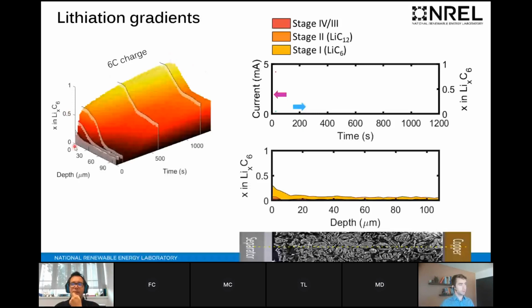So on this axis, we've got depth. 0 is close to the separator, 100 is close to the current collector, and then over time. And you can see at all times there's a severe lithiation gradient, but in particular at the beginning. Severe lithiation gradients where there's high lithiation close to the separator, low lithiation close to the current collector.